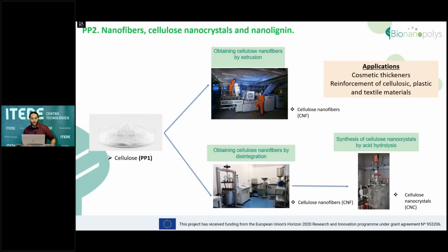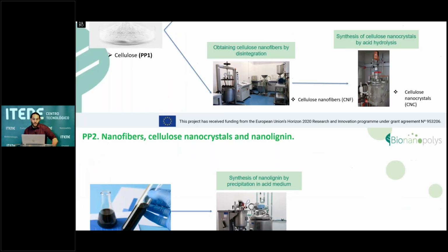This will happen in pilot plant number 2, where the cellulose obtained from pilot plant 1 will be converted into nanocellulose fibers. And these fibers, we can obtain them either by extrusion at one of our colleagues in France, or by disintegration, by mechanical grinding. This kind of cellulose nanofibers then could be further purified by acid hydrolysis to convert them into nanocrystals. This kind of cellulose additives can be applied into cosmetics or as reinforcers for cellulose and plastic and textile materials.